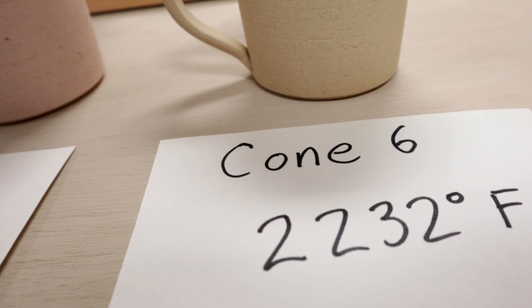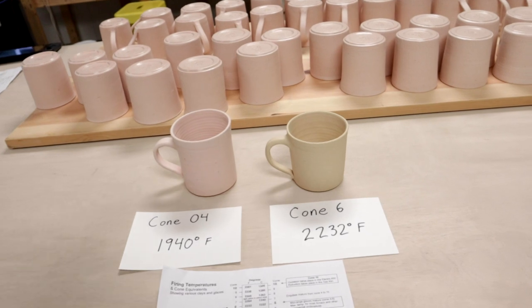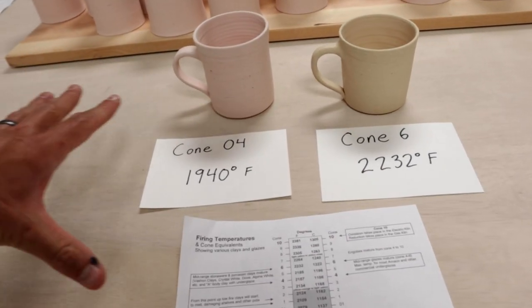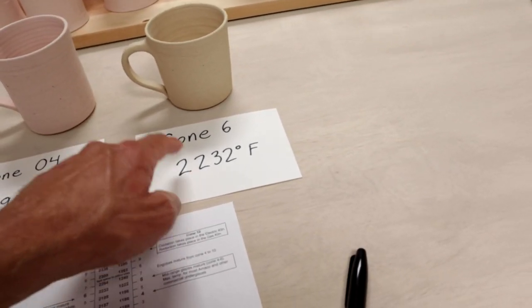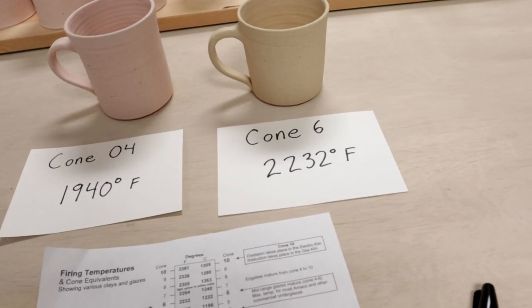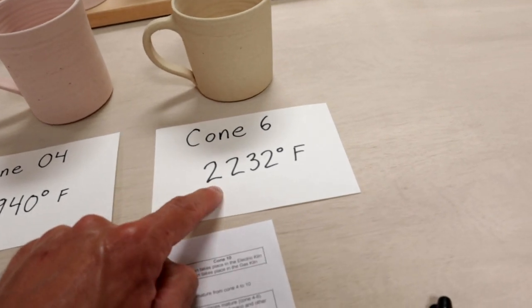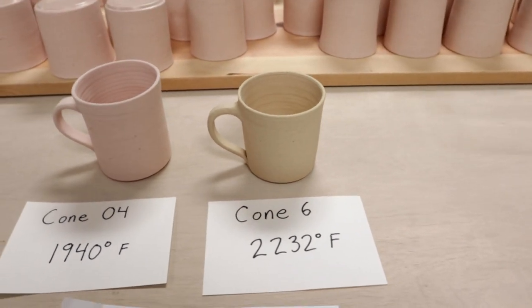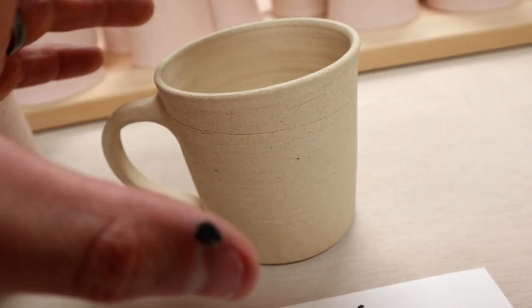As some of you know, I teach ceramics at high school, okay? And at our high school, everything we do is low fire. Our clay is low fire, and our glaze is low fire. So we just throw everything into one kiln, and it all works out perfectly. Everything is beautiful. The glazes I bought, however, are high fire glazes. And with everything else starting this business, I did not think about the temperature a lot. I just knew that my glazes were high fire. And so I did the initial bisque firing at the same high fire. That was a mistake because the ceramic was not porous and the glaze did not seep into this.